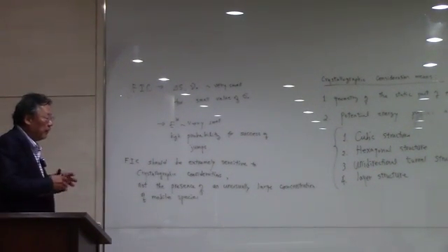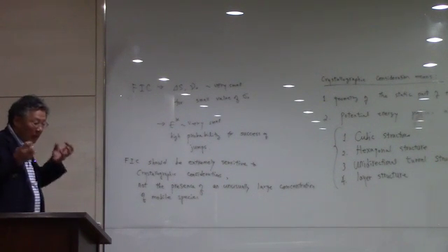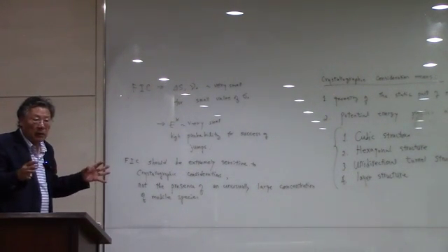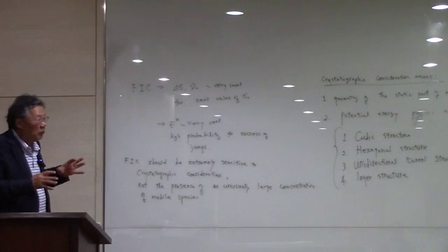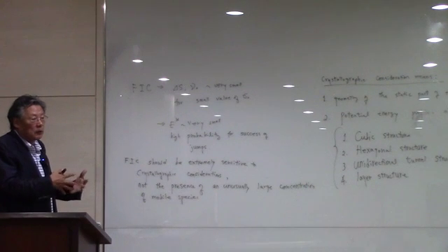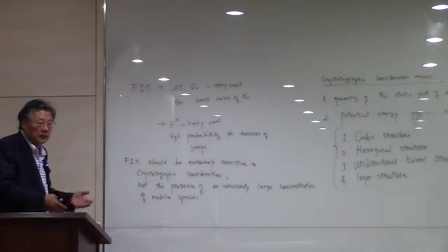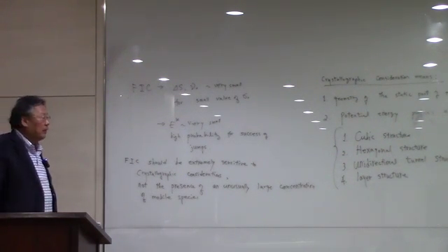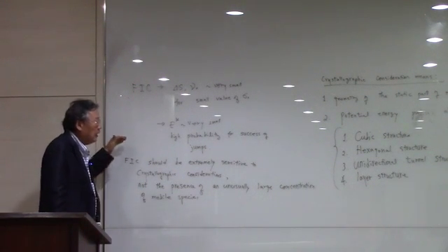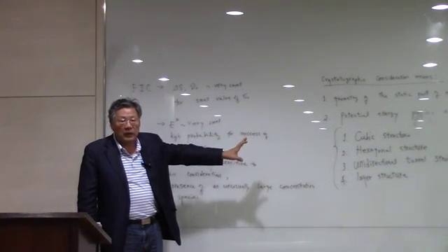Because in a simple hopping model, every jump is successful and every ion is mobile. We assume that, which is not realistic at all, right? But in a superionic conductor, we have very close numbers to that, or even higher numbers than the theoretical simple hopping model. Now, how can you explain that? The only way to explain that is to think about the open structures in fast ionic conductors.